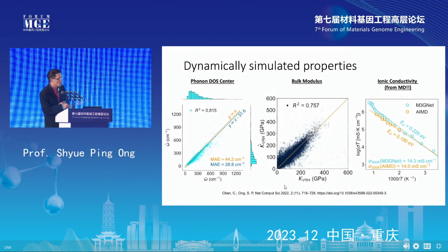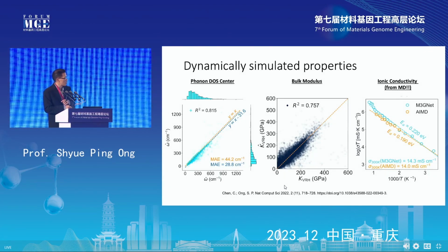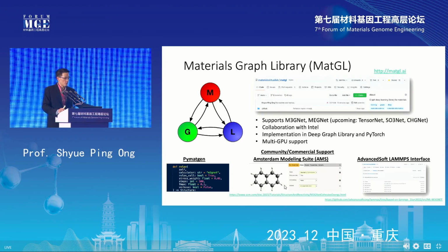We can calculate things like what is the phonon density of states, okay? Again, you can see that the agreement between the DFT and the M3GNet derived phonon density of states are in very good agreement. We can simulate things like the bulk modulus just from calculating the derivative of the energy with respect to displacements. We can even get ionic conductivity from MD simulations, okay? So this is an ionic conductivity of this solid electrolyte called Li3YCl6, and we can show that basically the conductivity that we get from our M3GNet simulations are very close to what you would get with ab initio molecular dynamics, okay?